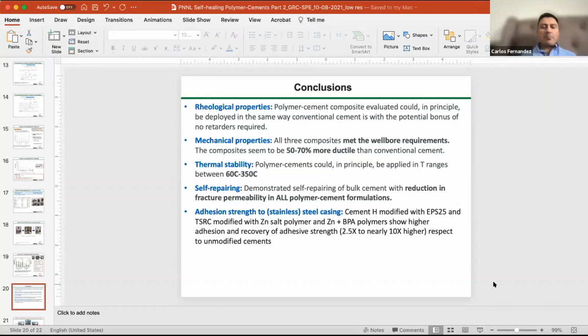Good question. We did both. We did the polymer alone, and we also cured some slurries with 5 to 10% of polymer. What we see is obviously the loss of water and bonded water, then water from hydration at higher temperatures, and then we see the decomposition of the polymer at very similar temperatures to the decomposition of the polymer without the cement present. So those temperatures are for both, either the polymer alone or the polymer with cement. We would anticipate that the polymer, since it's bonded to the cement, may be more stable than the polymer alone, but the decomposition temperatures were very close.